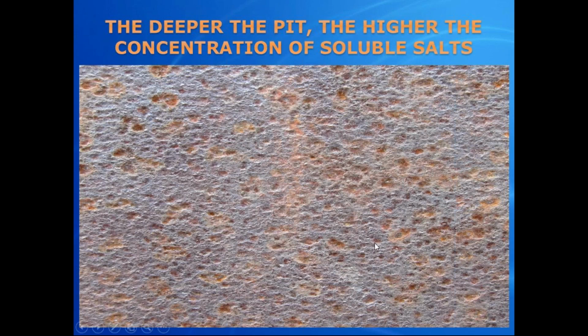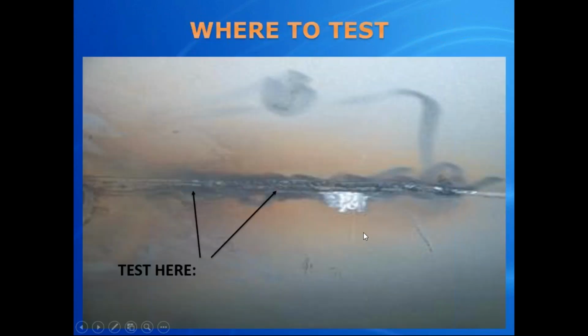This is a prime example of a piece of steel. You see the near white metal steel showing up on basically everything that doesn't have as much pitting in process, but where the deeper the pits are, the more concentrated the corrosion is taking place at a very rapid pace. And the deeper the pits, the darker the contaminant levels. And it's very obvious right here. And of course, where you test, you want to go and test where the harshest environment is. And that'll give you an example of what depth of corrosion you're dealing with. And of course, with weld seams, you always want to test around weld seams and within 2 to 3 inches